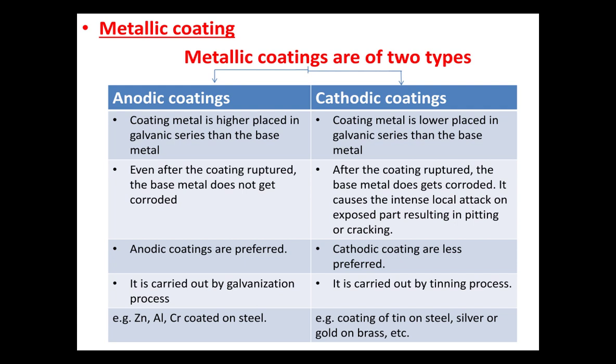It causes intense local attack on the exposed part, resulting in pitting or cracking. When corrosion is localized, it is called pitting corrosion. Anodic coatings are more preferred, cathodic coatings are less preferred. Anodic coating is preferred because even if the coating gets ruptured, the base metal is still protected. But if a cathodic coating gets ruptured, then the base metal undergoes corrosion. Anodic coating is carried out by the galvanization process and cathodic coating is carried out by the tinning process. Examples of anodic coating are coating of zinc, aluminium, chromium on steel, and cathodic coating is coating of tin on steel, silver, gold on brass.